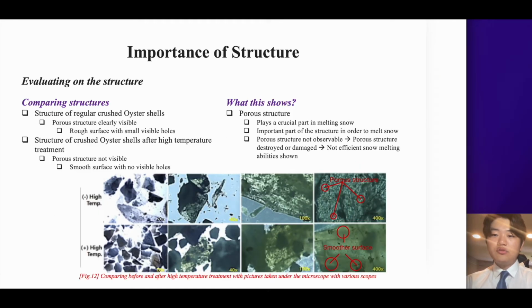When comparing the oyster shells with and without heat treatment in microscopic observation, for those without heat treatment, rough surfaces and small holes were observed. This is the porous structure of the oyster shells. When I observed the heat-treated oyster shells, smooth surfaces and no holes were observed. It is inferred that the porous structure has disappeared or been damaged. From the result that the ice melting rate decreased when no porous structure was observed, it can be confirmed that porous structure plays an important role in ice melting.